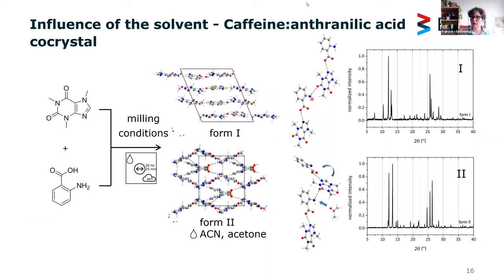And if you look at the hydrogen bonding pattern, it's the same thing in both structures. We have these chains, but here is a slight twist in the structure, and we hypothesize that there is an interaction between the solvent, even if it's a tiny amount, and this chain, and then we get a change in the local geometry, which later leads to the crystallization of a different structure.